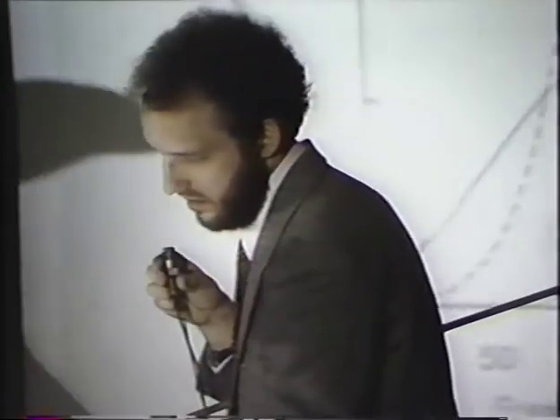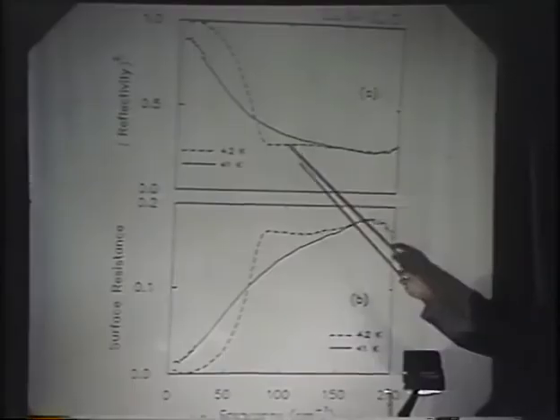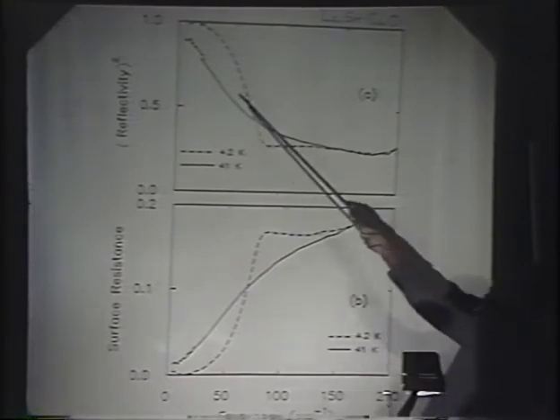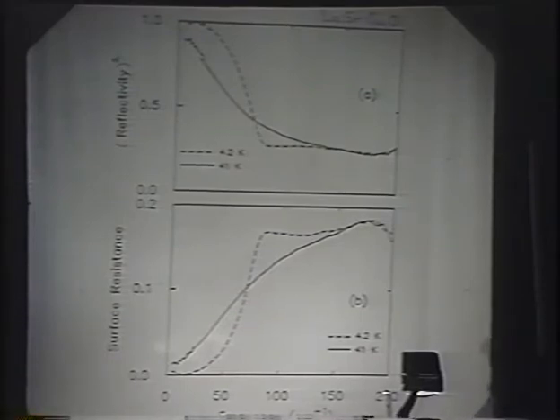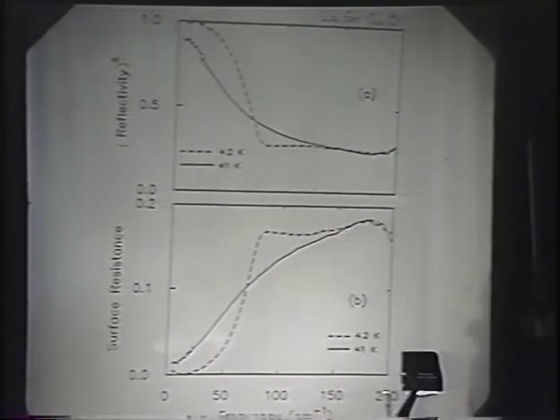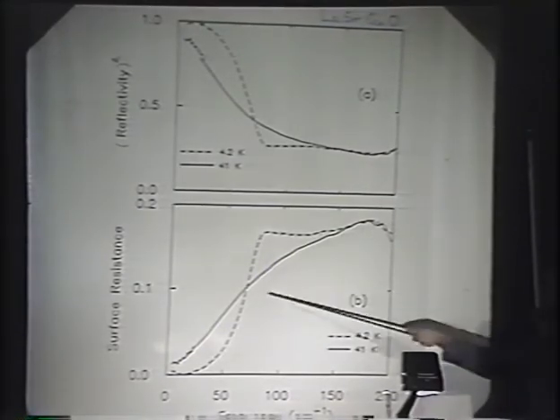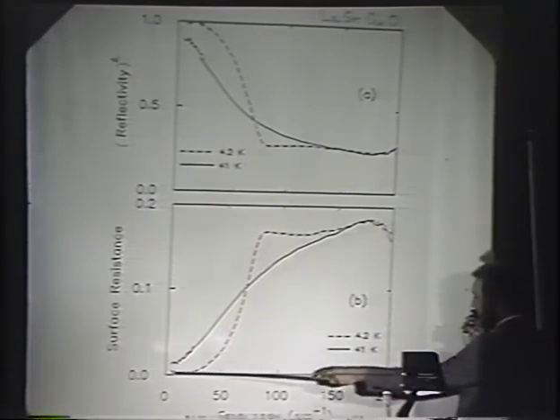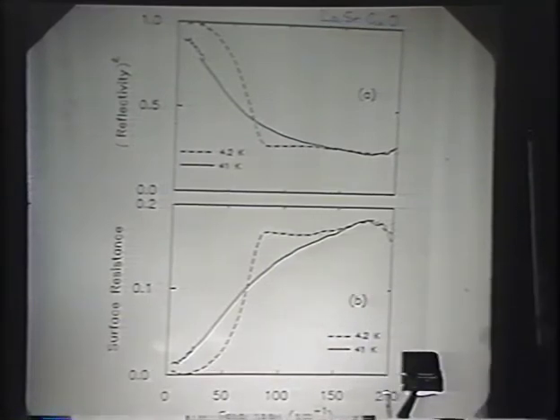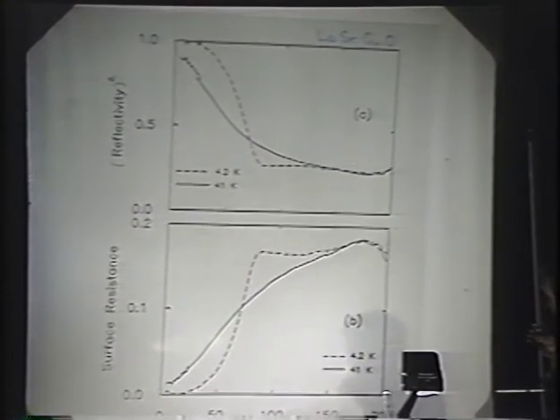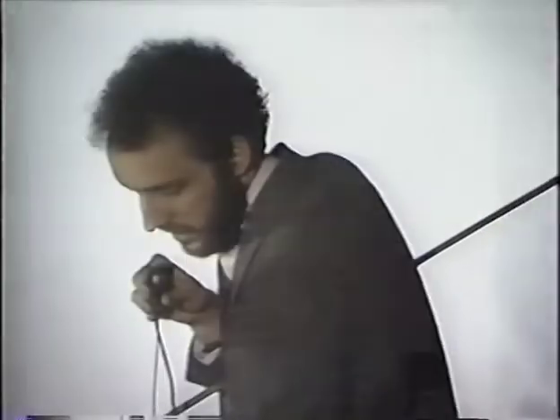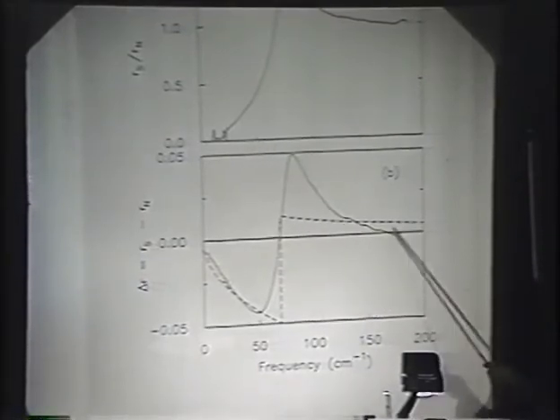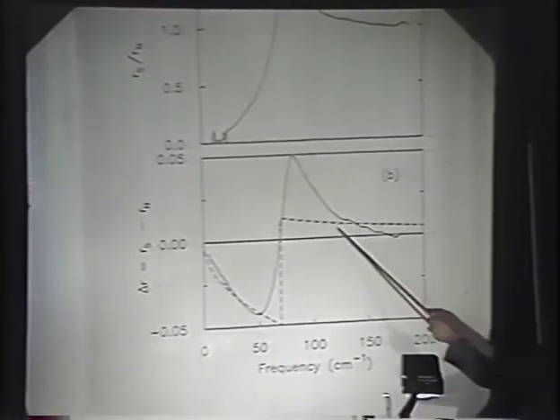So now we'll go to the data on the lanthanum strontium. First, you'll see the reflectivity squared because we have two samples that we reflect off of. The solid curve is the normal state at 41 K, and the dashed curve is the 4.2 K superconducting data. You'll see it's remarkably smooth. It's great data. So if we extract the surface resistance from this data, there's really zero absorptivity, and then an onset here. And it crosses the normal state absorptivity, as you can see. We can plot the difference in the surface resistance. We get this, the bottom curve here. And you can see that the areas are nicely conserved. So we believe that we've really extended out to the relevant frequency because all the area is accounted for.